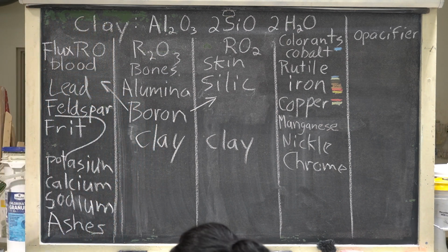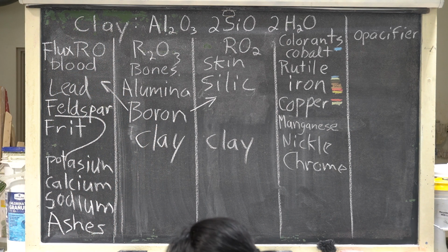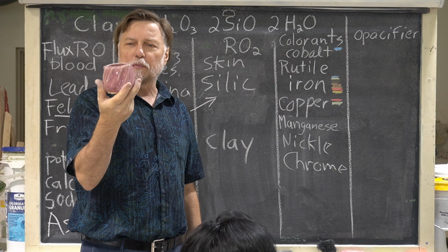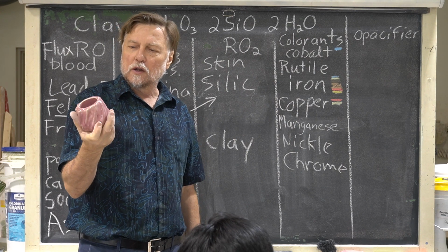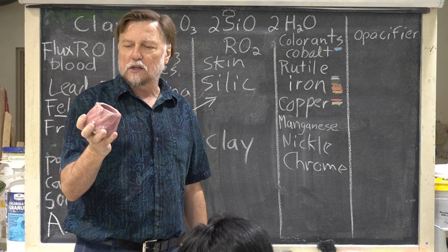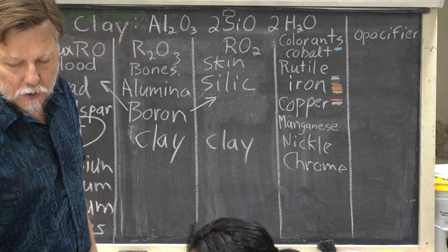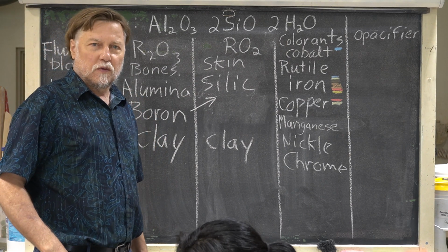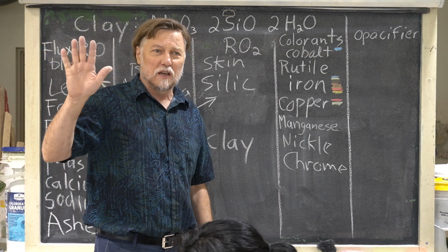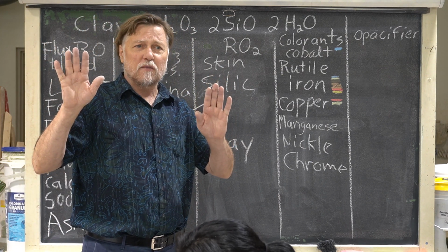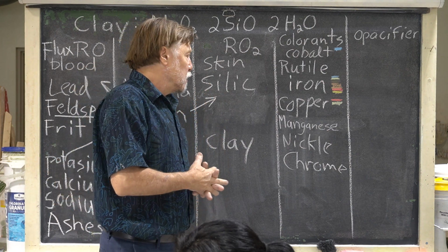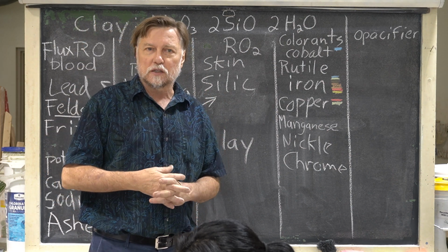I'll show you an example. This is a chrome tint pink, purplish pink. So that's a nice pink. That pink I don't mind. Some pinks are more like Pepto-Bismol. This one's a little bit richer. If you look close, you can see some variation in it. So this is chrome in the presence of tin. If you put like 15% tin and just a little bit, like 0.5% chrome, it will turn pink. You can get darker colors by increasing the amount of chrome.